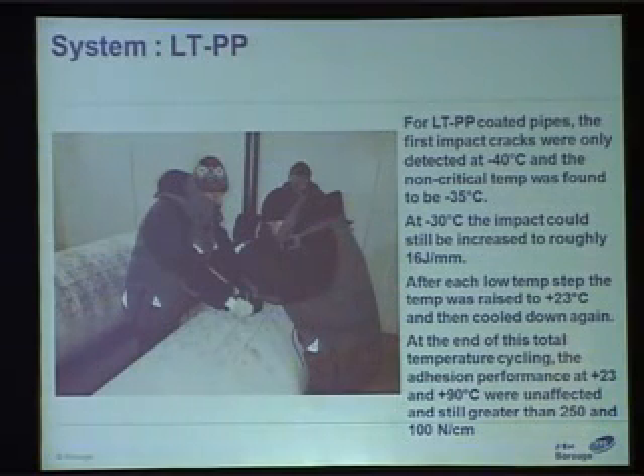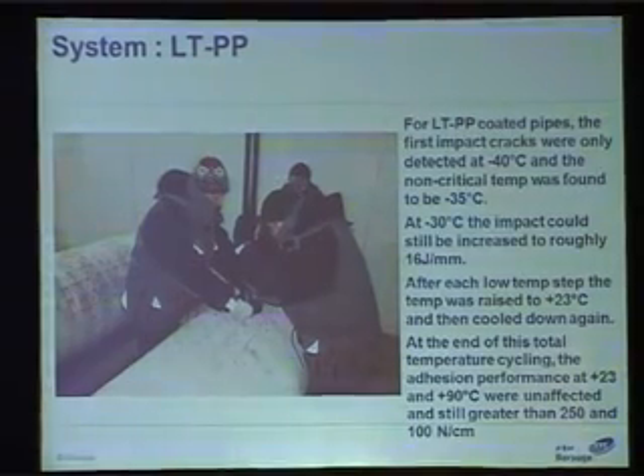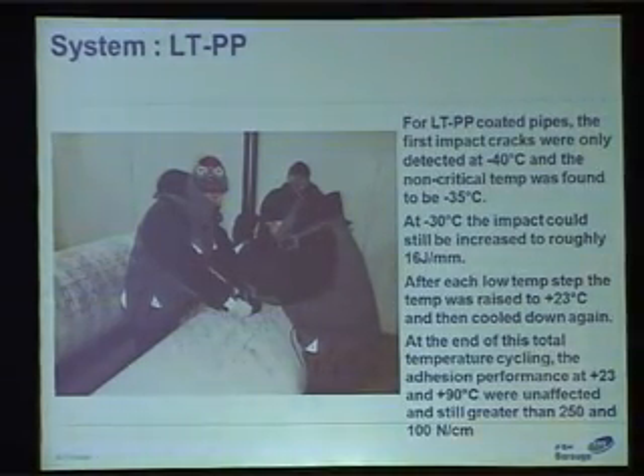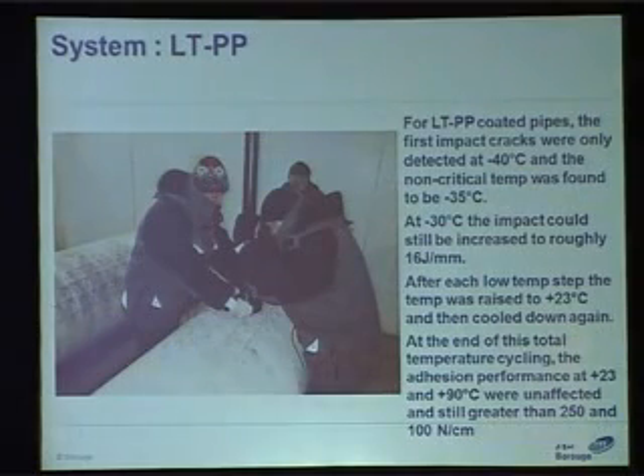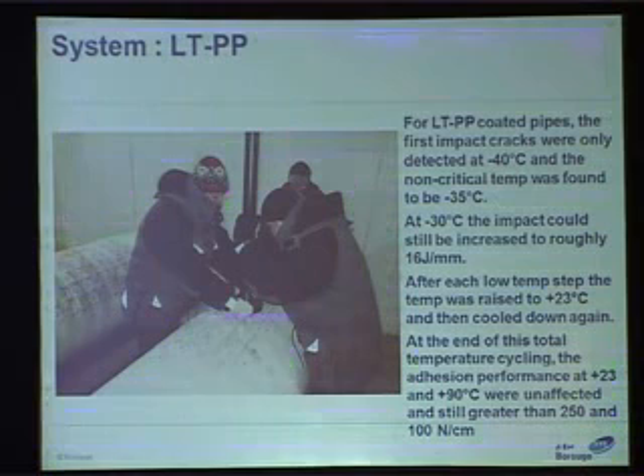For low temperature PP, the first impact cracks were detected only at minus 40 degrees centigrade. The non-critical temperature was found to be around minus 35. At minus 30, the impact was more than 16 joule per millimeter, which is still far above the requirement of the specification at minus 20. And after these many temperature cycles, the peel strength was tested and it was found unaffected and still more than the ISO requirement.